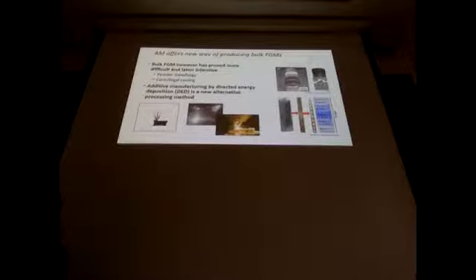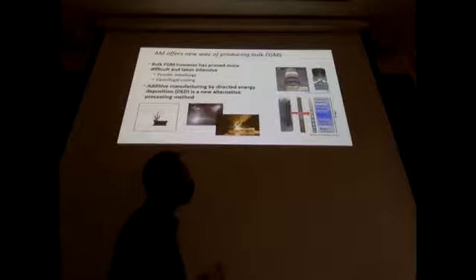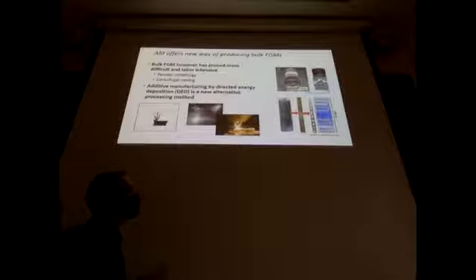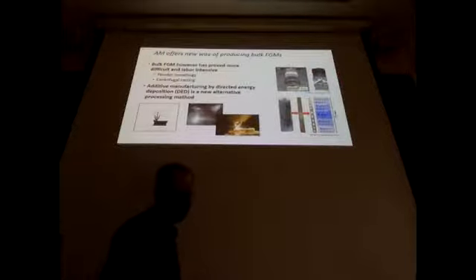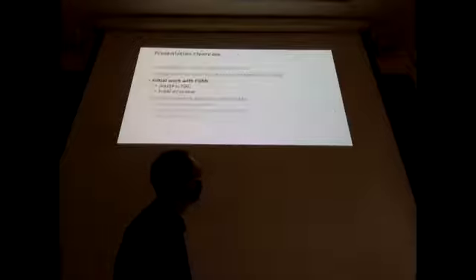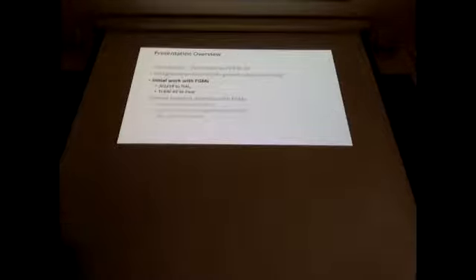So when I talk about additive manufacturing now, I'm talking about direct energy deposition. That's where you're supplying the material as either a powder or a wire, typically, and you have a heat source, which in the case I'll be talking about today is a laser. You're still doing a layer by layer process, but the benefit is that you can change the feedstock you're putting into that weld pool. Here is an example built by laser deposition, one by Alison Beasley in our lab, showing a 316. So now we'll go through our initial work on functionally graded materials.